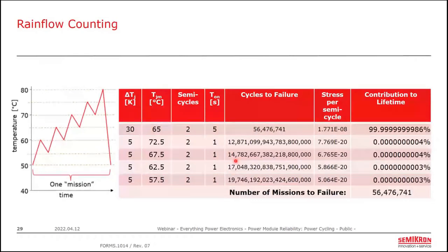And since we have a delta TJ, a TJM, and a heating time, we can just apply our loss model that we looked at earlier and get a number of cycles to failure that are valid for that particular cycle. If we take that number of cycles to failure for just that temperature cycle and take its inverse, one over that value, we get the effective, quote unquote, stress per cycle. And we can then take the inverse sum of all of these and get a total amount of stress due to all of those cycles.